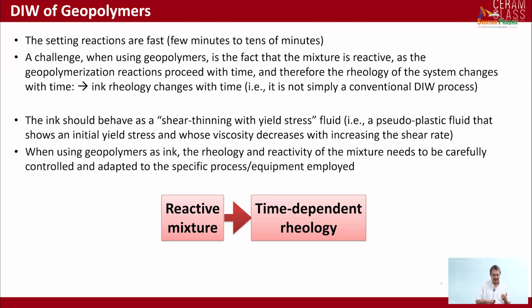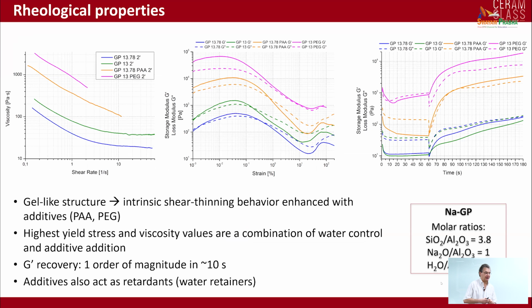I already mentioned that. And I told you that geopolymer gels, especially at the beginning of the reaction, are reversible gels. So if you apply stress, you break the bonds. And when the stress is released, the bonds reform. But this type of behavior is not fully suitable for creating suspended struts. And since we are interested in using this approach for making filters, we need to be able to obtain that type of microstructure.